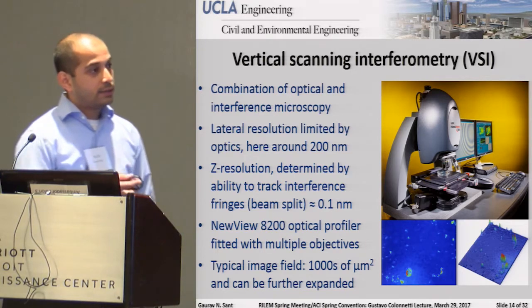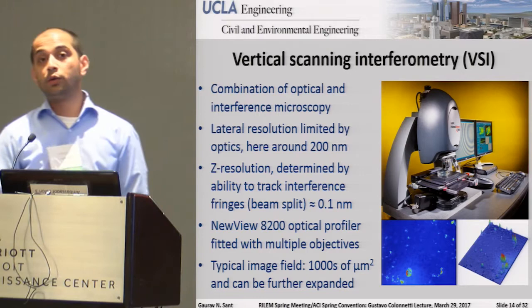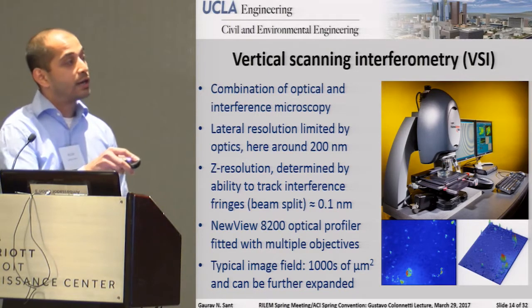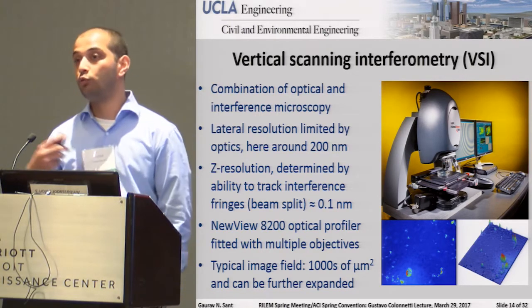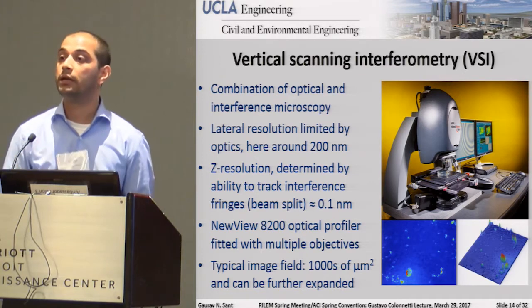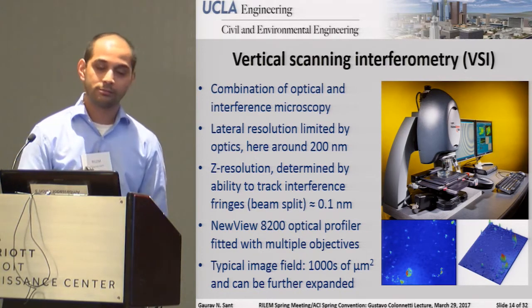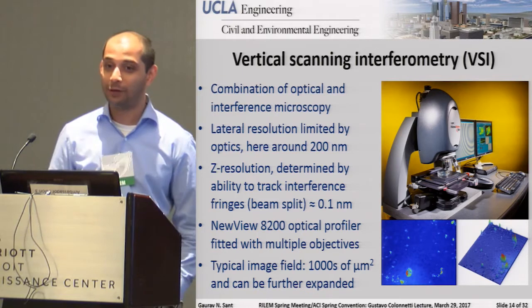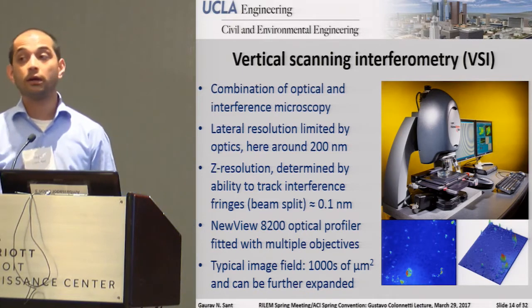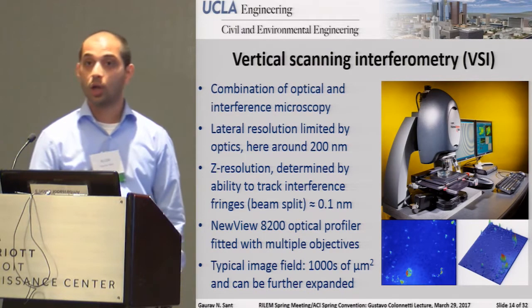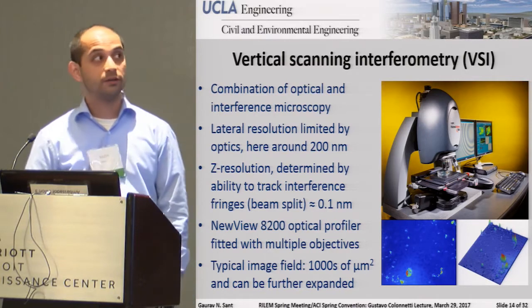The other thing which actually makes these interferometers very, very powerful is that you can do very large areas. So you can do areas which are thousands of microns square. So we will routinely look at areas which are, for example, a millimeter by millimeter. And while that sounds very small, I assure you it's actually really, really large. And you can do this in real time. So you can actually do it as surfaces dissolve away, and you can see what happens on a surface.